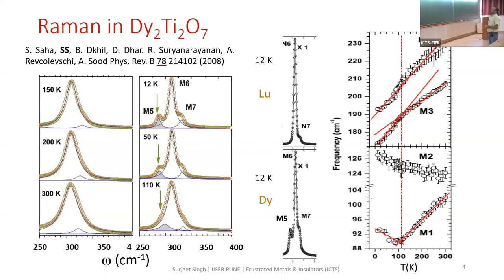And the other point to notice is that in lutetium, this is the section of the spectra at 12 Kelvin, you don't see this new mode, which is designated here as M5. So this is unique to the spin ice pyrochlore, dysprosium 2 titanium 2 oxygen 7. You can also notice this graph shows the line shift of various Raman active modes as a function of temperature. You can see anomalous softening for most of these phonons, and you also see changes taking place precisely at the temperature where the new mode appears.